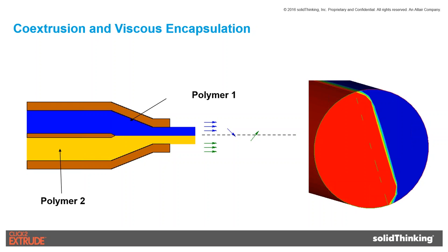To show the viscous encapsulation effect, here I'm showing one simple example where 2 polymers are coming in, not touching in the first place, and they join at this region and come out. If the polymers are of the same viscosity, and I pump the blue one at 10 millimeter per second and the yellow one at 20 millimeter per second, because of that difference in velocity, the interface between them will shift in the upward direction. And that's what we are seeing here. So this yellow is getting a deformed shape, becoming red. It is taking the area, shifting the interface between the two polymers, and that's how it's coming out.